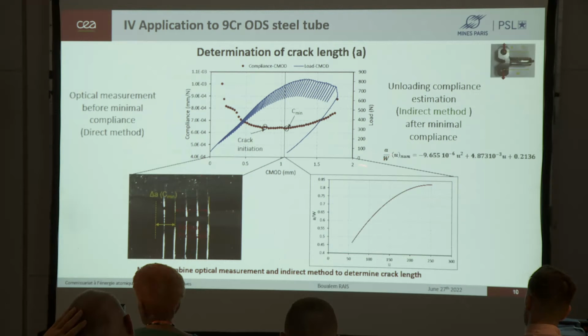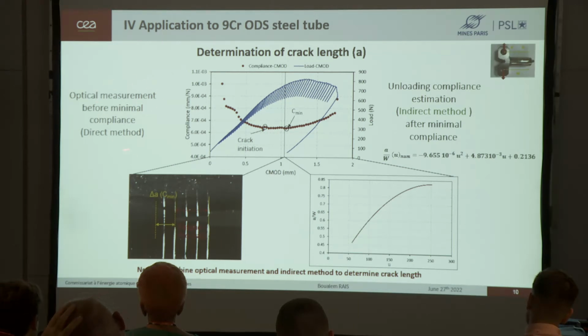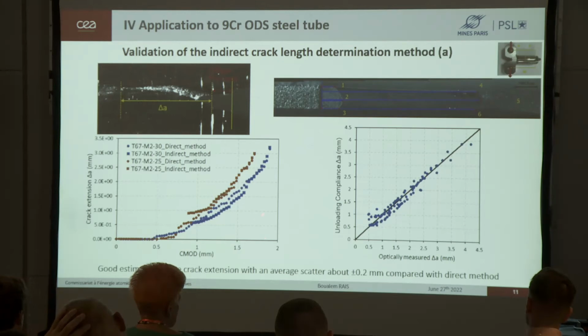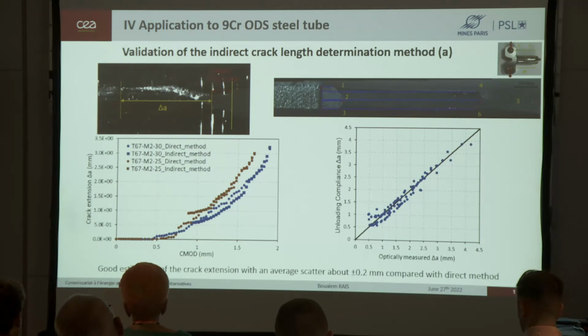First, we observed during our experimental campaign that we have a crack initiation that occurs before reaching this minimum compliance. So this obliged us to use some optical measurements that we call a direct method to have the crack extension before reaching this minimum compliance. Beyond, we use our unloading compliance method, or indirect method, presented before to determine our crack extensions. To validate this indirect method, we compared the optically measured crack extensions to those estimated from unloading compliances.